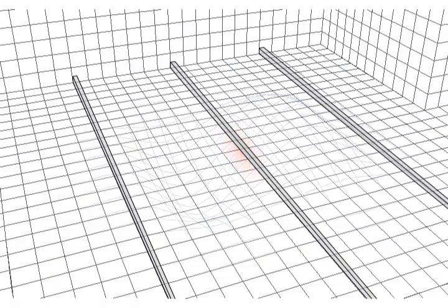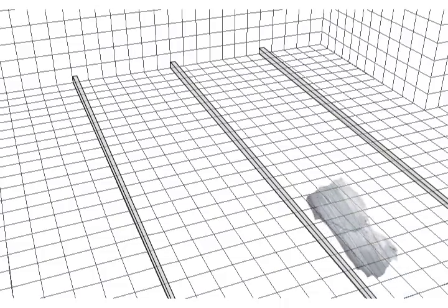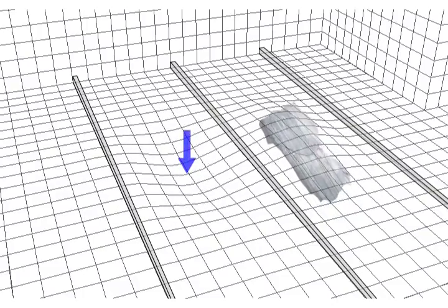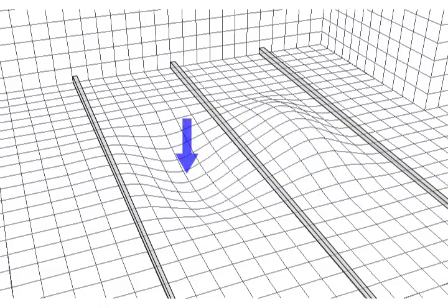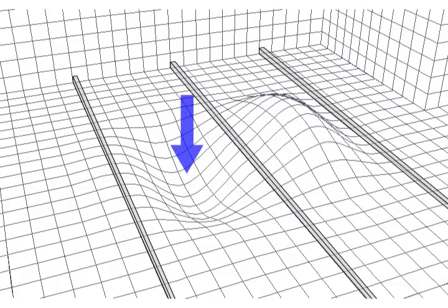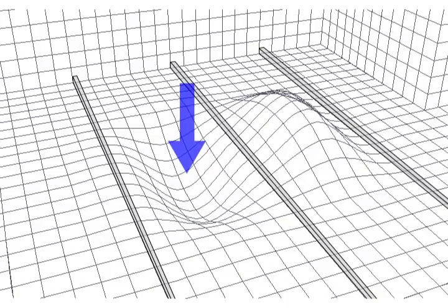The second physical process identified by investigators was referred to as a hydrodynamic pressure surge, and is a consequence of an essentially full fuel tank, sudden inward deflection, and the presence of an incompressible fluid — jet fuel — which is being displaced by the deflection. The rapid inward deflection and incompressible jet fuel being displaced causes a rapid pressure rise, especially in the immediate area adjacent to the deflection.